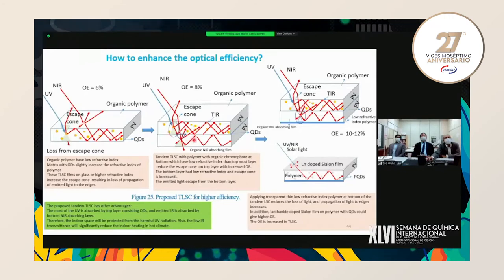If we have tandem-based with organic NIR absorbing film without quantum dots, then as compared to the top one, the bottom has low refractive index material. So the escape cone will be less and more total internal reflection will occur and the light will propagate to the edges. So we can increase, for example, if we have 6%, then we can have around 8%. Even if we have low refractive index polymer coated on the bottom, then it will also decrease the escape cone. So we can increase the efficiency around 10 to 12%, even with lanthanide doped sialon films.